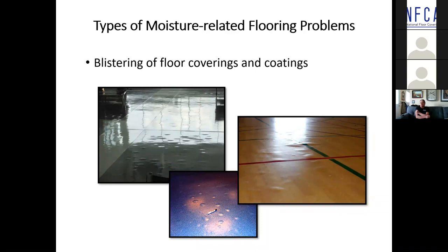Blistering of floor coverings and coatings. It's far more common for osmotic blisters to develop in polymer flooring than it is in resilient, but they still can happen in resilient. That picture on the left is a 3/8 inch thick epoxy floor. That's the Baltimore rental car center. What kind of pressure does it take to debond 3/8 inch thick bonded epoxy flooring? People say, oh, it's vapor pressure. I said, no, it's not vapor pressure. Even at 100 degrees Fahrenheit, 100% relative humidity, vapor pressure is less than 1 psi.